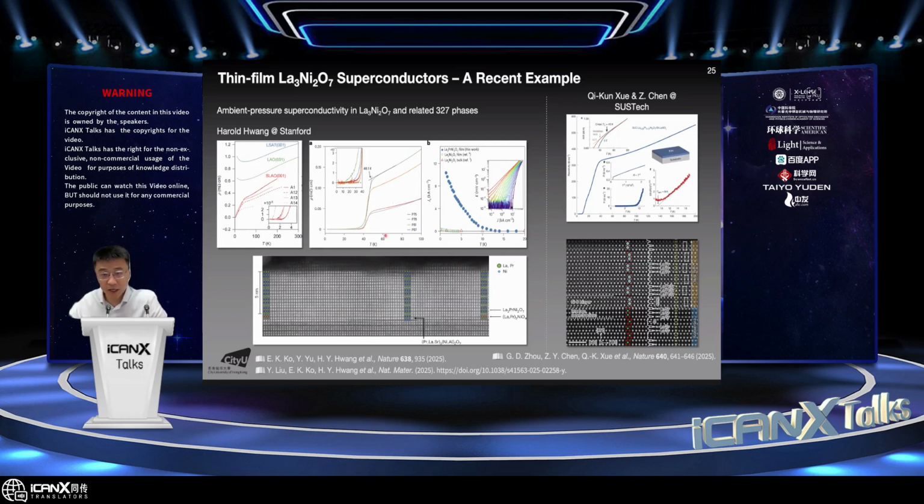So this is already remarkably higher than, let's say, the first superconducting nickelate discovered in 2019, which back then had a Tc of 15 to 19 Kelvin. So these are very recent examples in the very fast developing field of nickelate superconductivity. People are trying very hard, day and night, to grow different materials and hopefully raise the transition temperature as close as possible to liquid nitrogen temperature or even above.